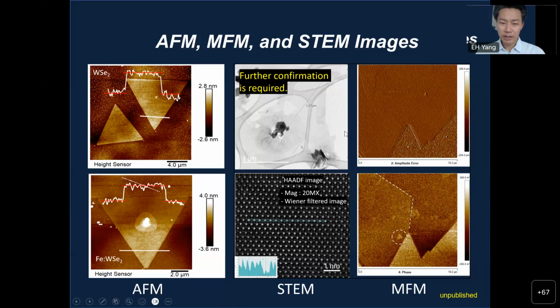And on the center, we still need more work, because our collaborator doing this aberration corrected STEM imaging, and they had some construction in the site, so they couldn't get the very nice image. This is nice enough, but we need further confirmation. So this also shows the quenching here. That means you have iron here, okay, that replaces tungsten, but it's not. It's a little bit. I'm not 100% sure. This may be error, so we'll have to see.